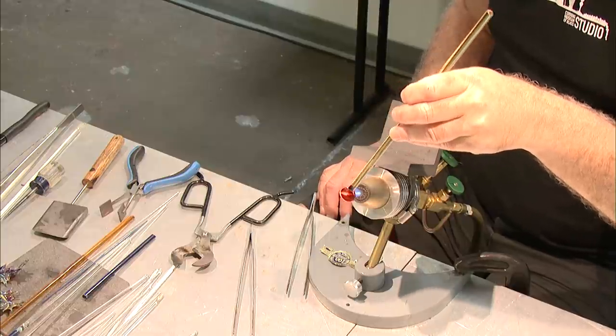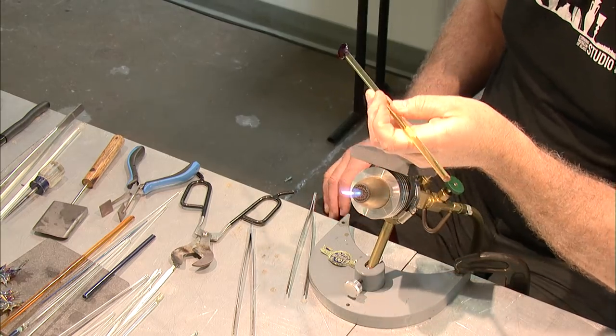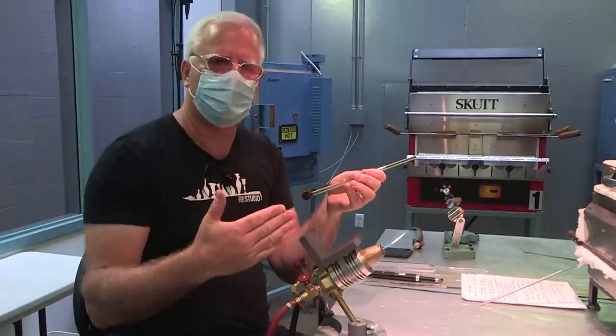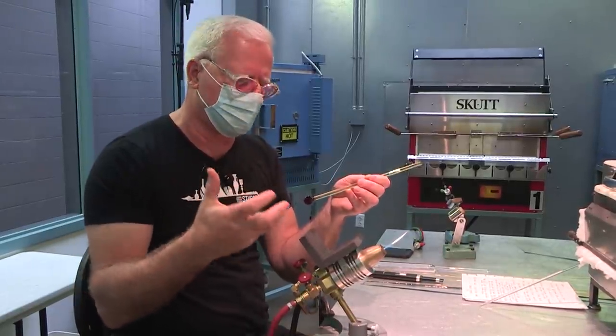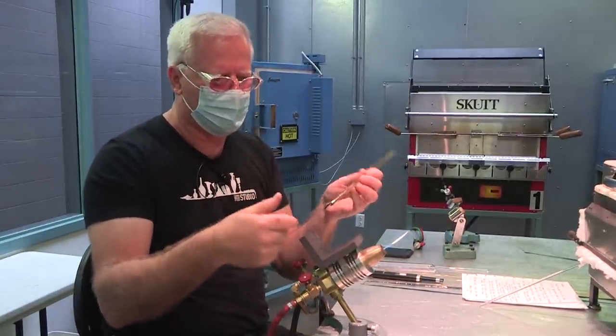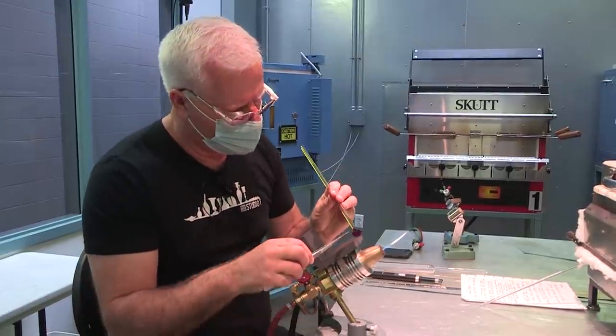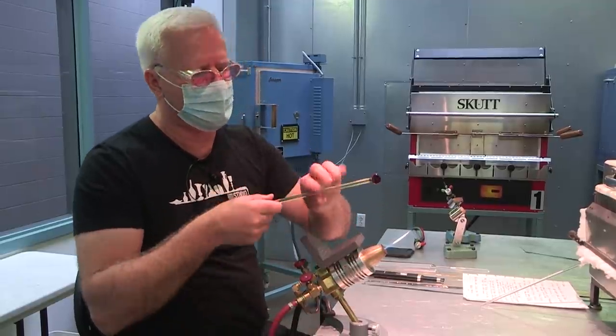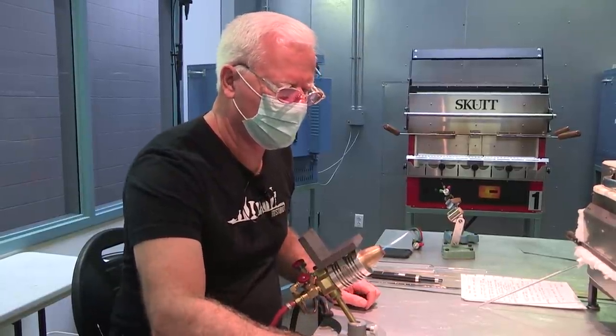Okay. And so you might say, well, Stephen, that's just completely amber. There's no purple in that at all. The next step is to wait for it to actually cool. And as it cools, it starts to bloom into those other colors. So as we're doing that, and you can already start to see that it's happening here, these clouds. All right. What I'll do is I'll set this aside and we'll reduce the other.